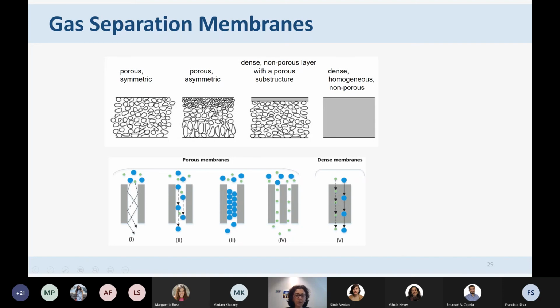So what we are aiming for is to create a dense layer on top, very, very thin, so that the gas just takes very little time to pass from the top to the bottom, and then I have this porous support that is just supporting our very thin membrane. And with that, I can have very different permeation mechanisms. I can even combine some of these mechanisms. What would be ideal is to combine the mechanism of the dense with the Knudsen diffusion, and that's what we are aiming at.